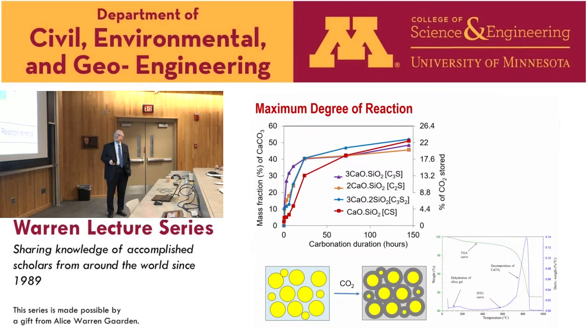So I will start by talking a little bit about the reaction kinetics. How is that reaction happening? So we look at all those materials that we produced and look at how they carbonate, how quickly they carbonate, what is the mass fraction of calcium carbonate or limestone that we are forming. And if you look at those curves, you can see that they are clearly showing two slopes, right? There is a rather steep slope in the beginning, and then there is a less steep slope at the end. And not only that, you can see that the separation of those points at the end is much closer than the initial separation of those points.